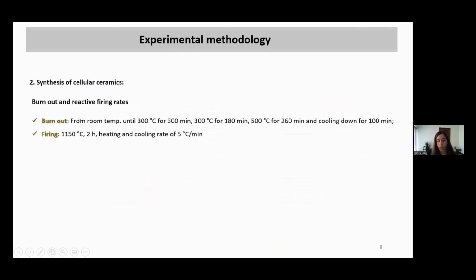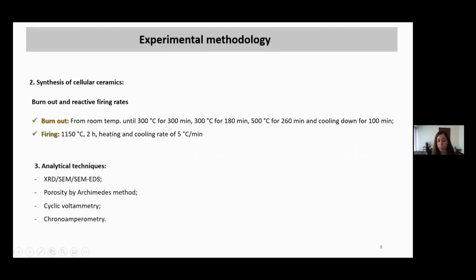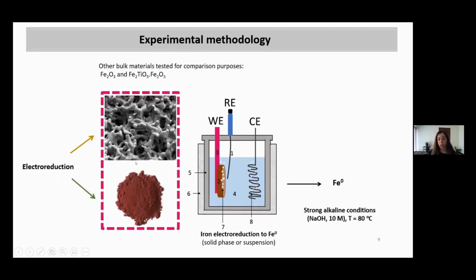In terms of burnouts and reactive firing rates, these are the rates used. For the pseudobrookite firing, we use 1,150 Celsius degrees. And in terms of analytical techniques, we use XRD, SEM, EDS. We study porosity by the Archimedes method. And we also use cyclic voltammetry and chronoamperometry studies. So as I said, we use these two modes, the bulk in pellets and in suspension. However, in the bulk reduction, we compare it with highly porous hematite, and highly porous composites of pseudobrookite in excess of hematite, just for comparison purposes, and these occur only in bulk, not in suspension. So in suspension, we used only pseudobrookite powder.